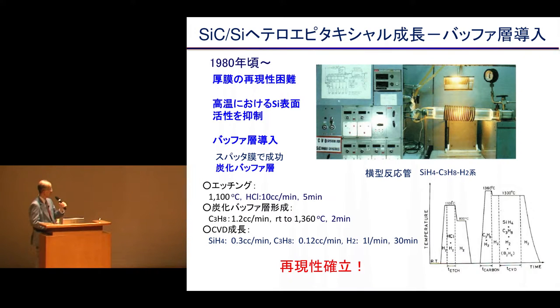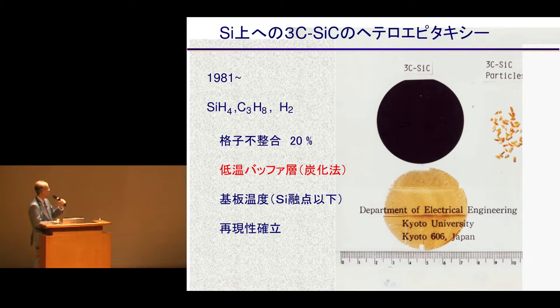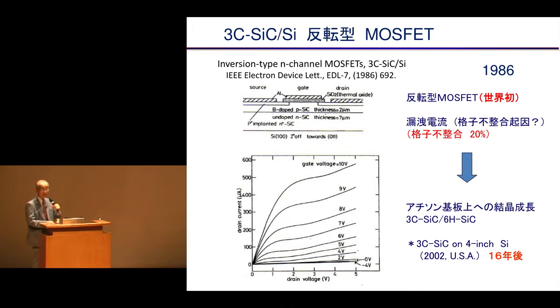I introduced a buffer layer so that silicon carbide could be developed on a different material substrate. And it was about 1980 that we succeeded. So we were able to use the handmade reactor to develop reproducibility on a silicon substrate. Silicon carbide was grown. So we succeeded in that.